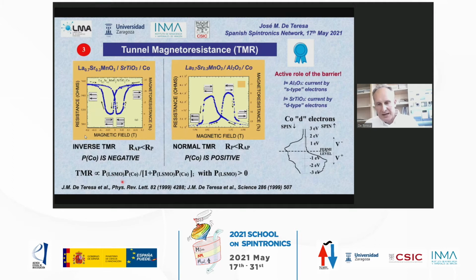Good. But in some experiments a few years later in which I participated, we discovered that this simple model was not enough to explain the results, because we observed that the insulating barrier was also playing a role. So we decided to study two ferromagnetic electrodes, manganite and cobalt. Manganite because it was supposed to be a half metal, so spin polarization equal to 1, and cobalt because it could give a good temperature dependence. And then we prepared these samples with different barriers, such as strontium titanate or aluminum oxide.